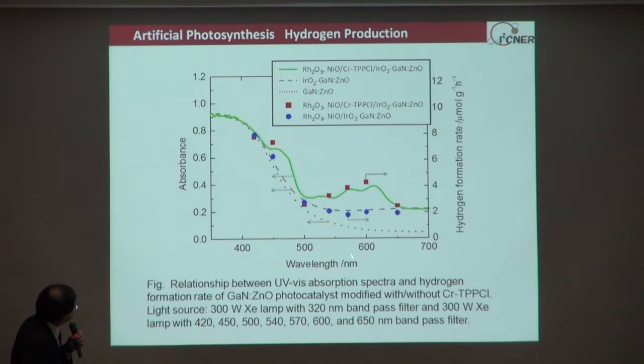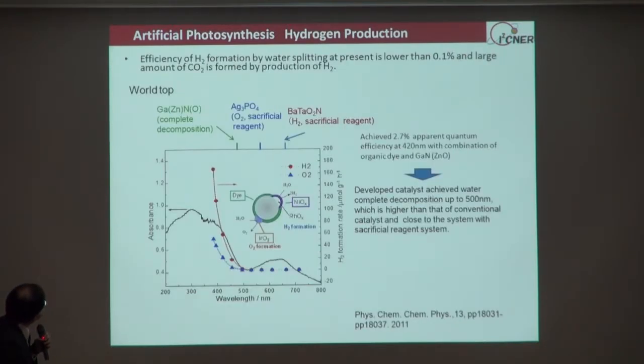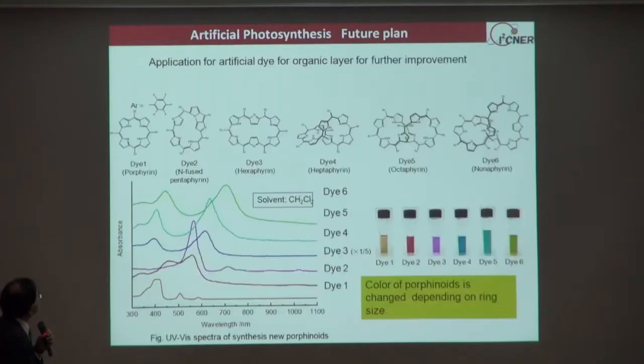And then if the inorganic dye excitation is done at further higher wavelengths, then we can obtain hydrogen and oxygen by using the higher absorption wavelengths. And also, what I show here is the world top level of the absorption wavelength of each catalyst, and 600 is almost the highest reported in the open literature.